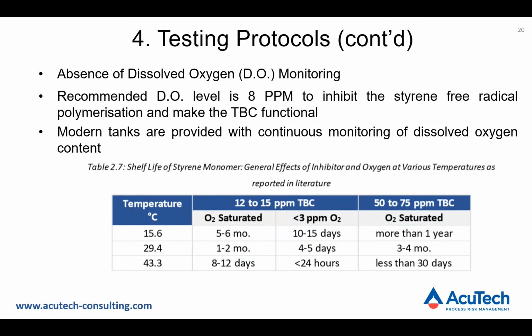Another issue with styrene is that when it is exposed to heat, it forms free radicals. These styrene radicals react either with oxygen to form peroxide radicals or with styrene to form the polymer chains. In the presence of sufficient oxygen, the peroxide formation is significant because this reaction of peroxide radical formation is much faster compared to the polymer formation with styrene. So oxygen works as a polymerization inhibitor, while TBC controls its efficient use.